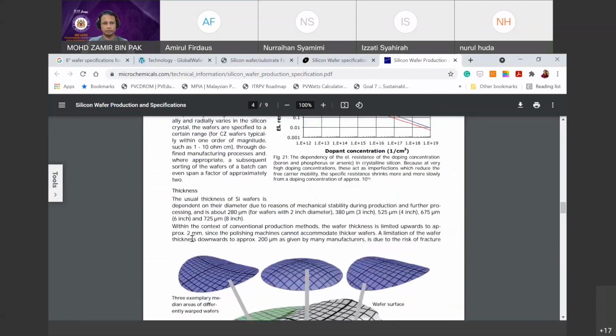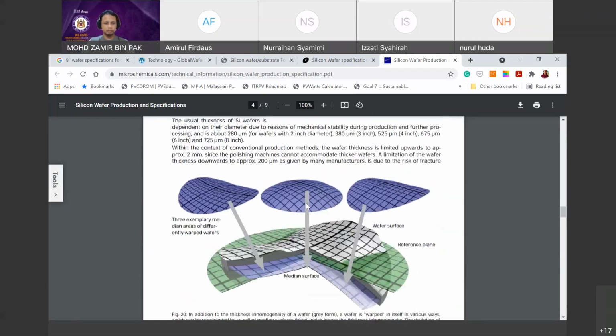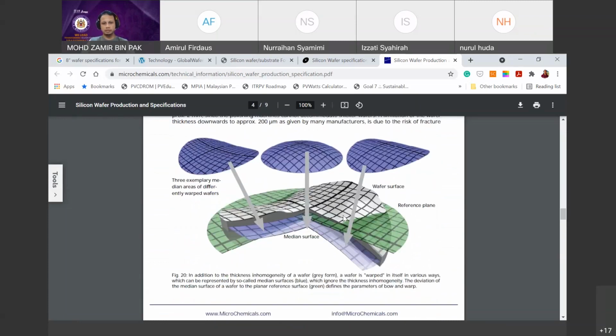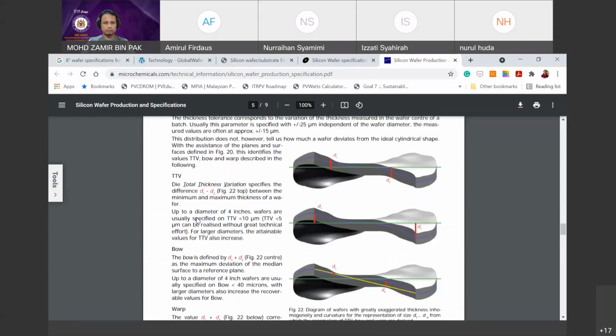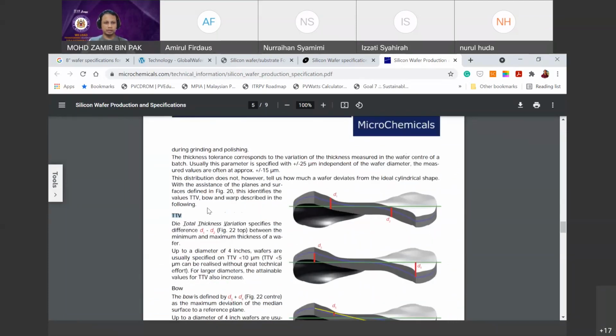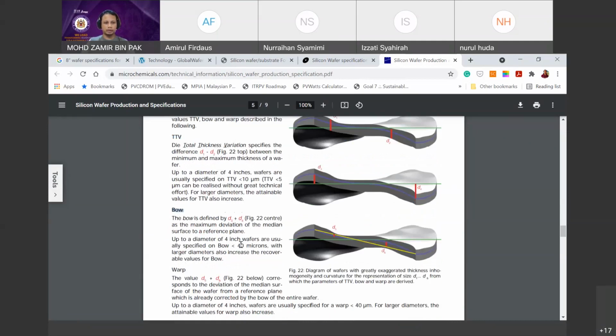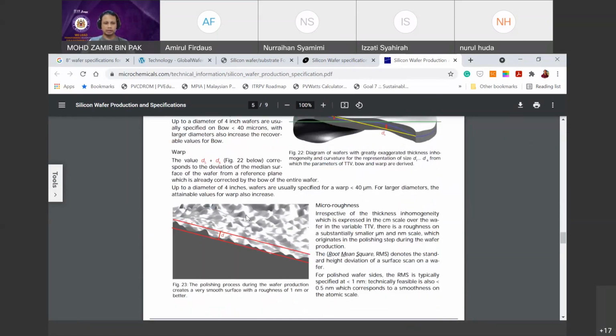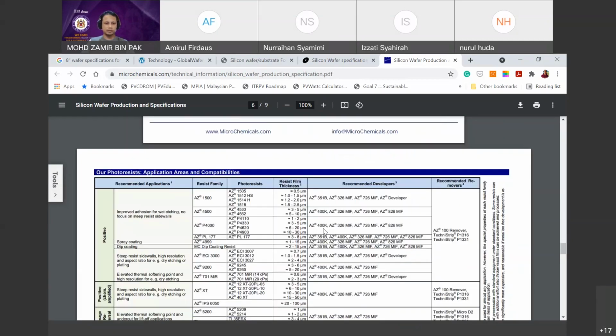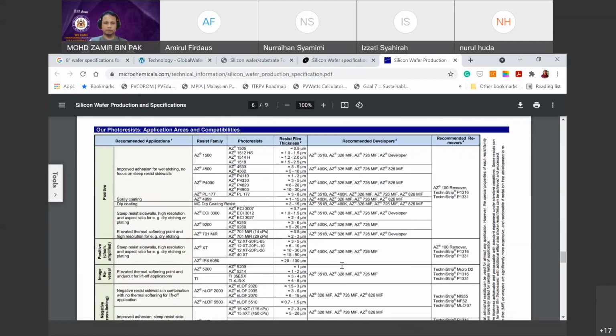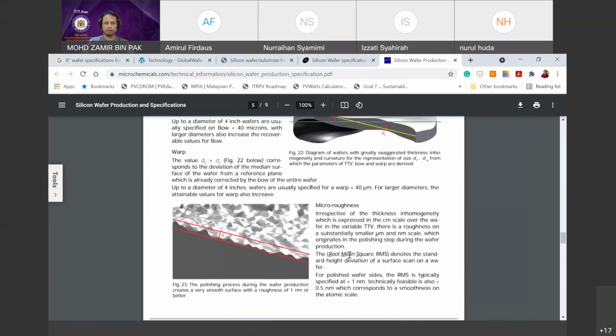So let's see this. So thickness variation, total thickness variation, TTV, bowing, right? I'll upload this PDF later on the e-learn. You can see what is bowing, how is it measured and stuff like that. Warping, micro roughness, less than 1 nanometers now. So you can see the micro roughness. Even though you've done the lapping process, it will still show you some micro roughness with a tolerable level, right?